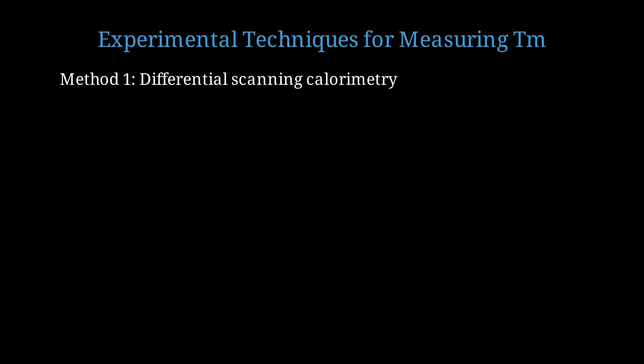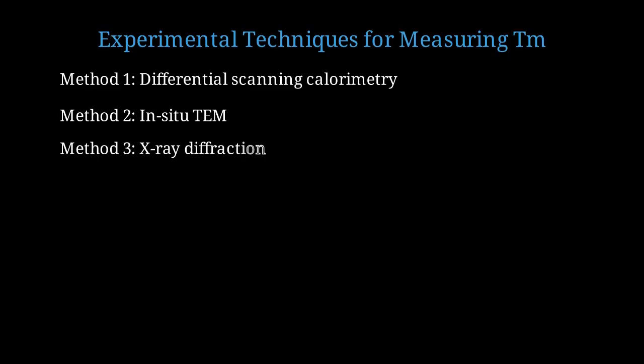How do scientists actually measure these melting points? Several techniques are used. Differential scanning calorimetry, or DSC, measures heat flow as temperature increases. A peak indicates melting. In situ transmission electron microscopy allows direct observation of melting in real time at the nanoscale. X-ray diffraction monitors the disappearance of Bragg peaks as the crystalline structure melts into liquid. Computer simulations using molecular dynamics can predict melting behavior and validate theoretical models.